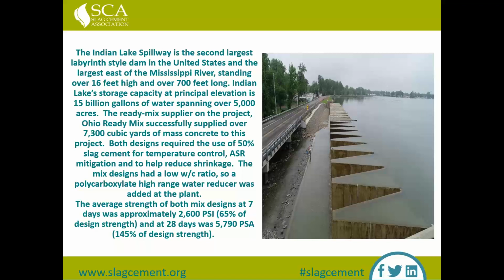This was a 4,000 PSI design for 28 days. They were getting average strengths at 7 days with this 50% replacement level of 2,600 PSI, and then more than doubling that at 28 days. So they were well in excess of the 4,000 PSI design strength on this one.